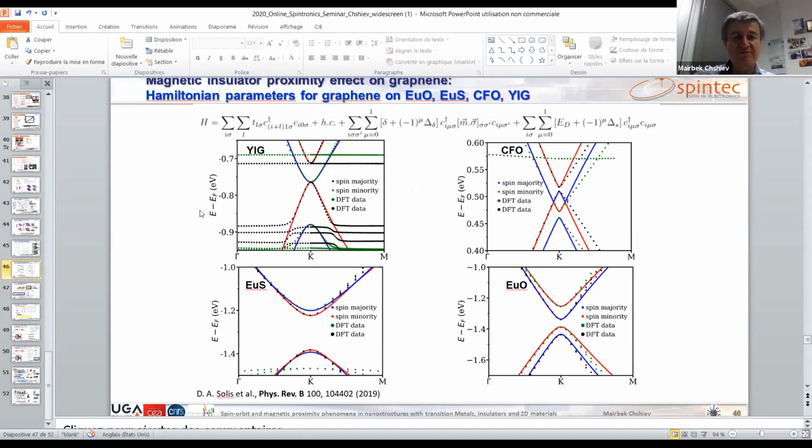So let's look at the yttrium garnet here, bands. In our paper, we gave all the conductances resolved for all the contributions. You see that we have this almost half metallic region. You put your Fermi level here, and you will have only majority band, while here, you will have only minority state band. Now imagine you magnetize your graphene by putting it parallel or anti-parallel. Obviously, it will work similar to a classical spin valve in some sense. So that is an explanation.